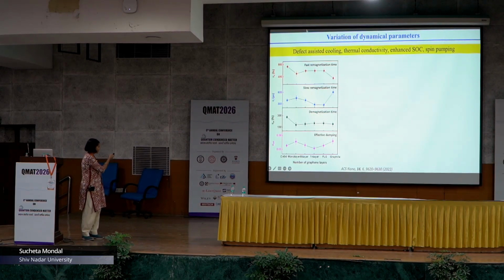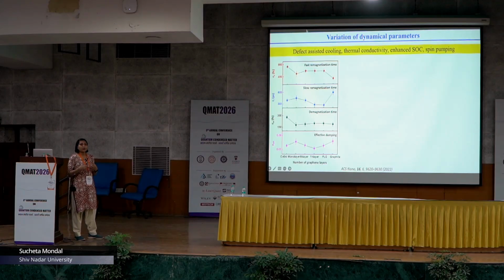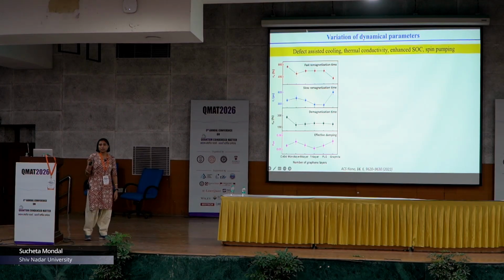Yes, so I will be done soon, I hope. So, this is the effective damping which is non-monotonically varying. Our assumption or interpretation is that monolayer graphene is weakly spin orbit coupled, but when it is adjacent to another substrate, there are substrate induced effects and layer induced effects which are enhancing the intrinsic SOC. So, this is the extrinsic SOC which is increasing the damping.